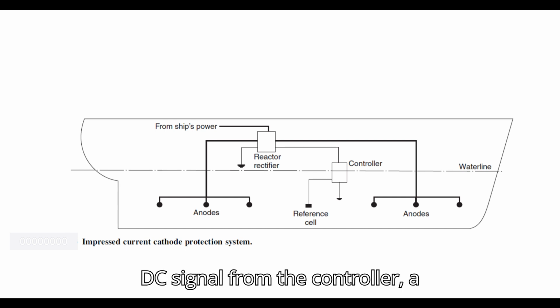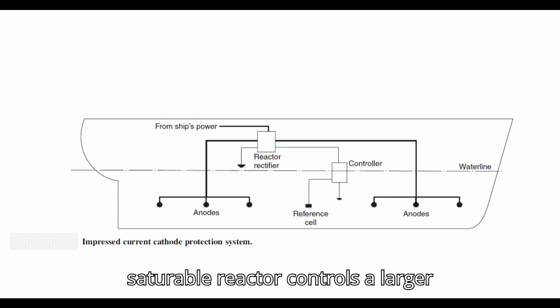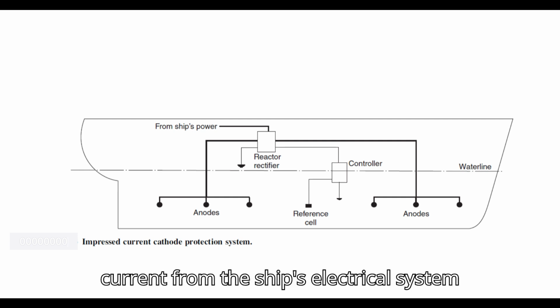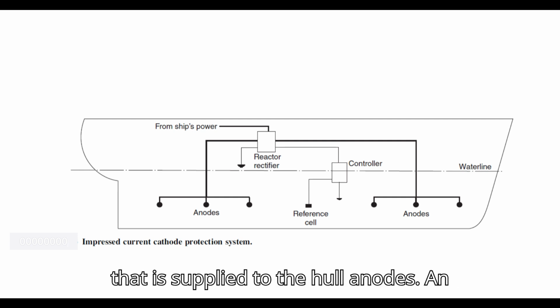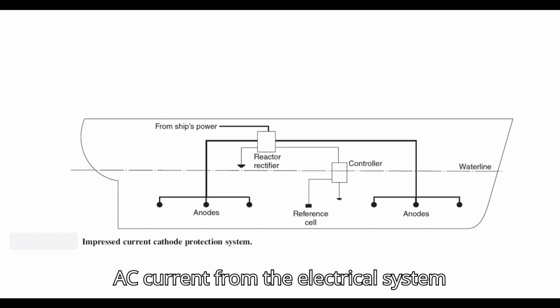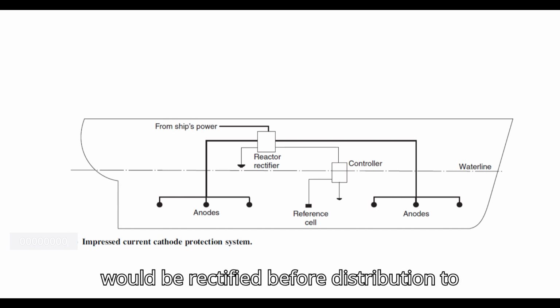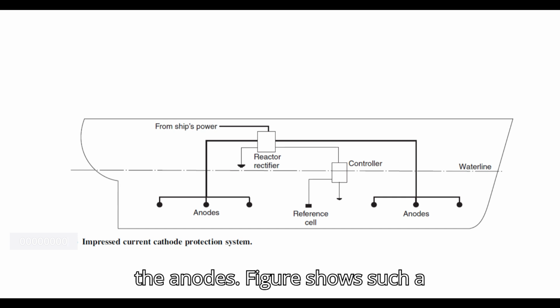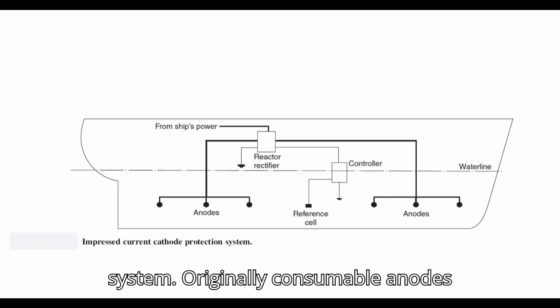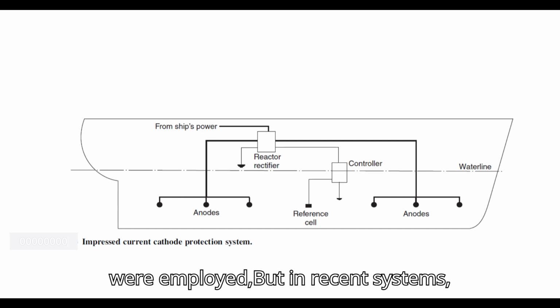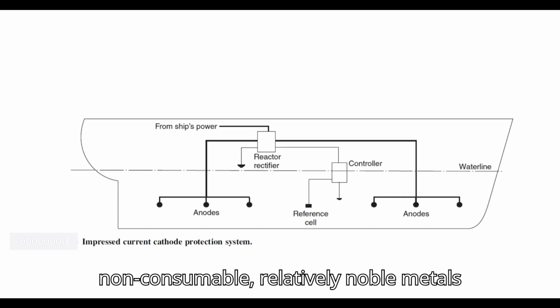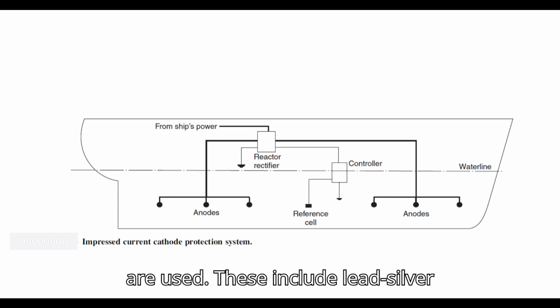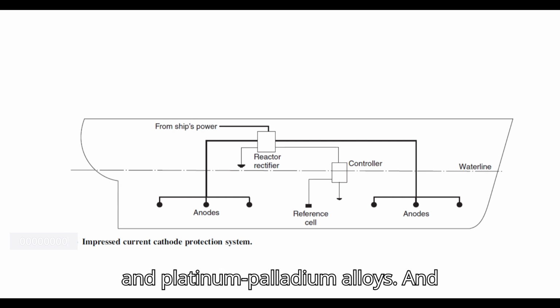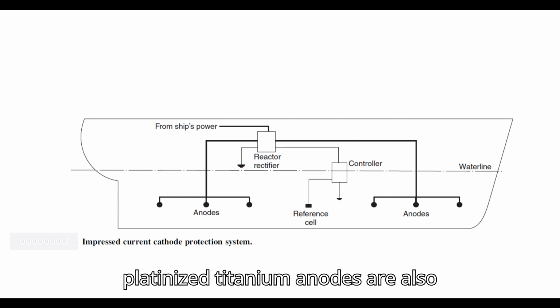Using the amplified DC signal from the controller, a saturable reactor controls a larger current from the ship's electrical system that is supplied to the hull anodes. An AC current from the electrical system would be rectified before distribution to the anodes. Figure shows such a system. Originally consumable anodes were employed, but in recent systems non-consumable relatively noble metals are used. These include lead-silver and platinum-palladium alloys. And platinized titanium anodes are also used.